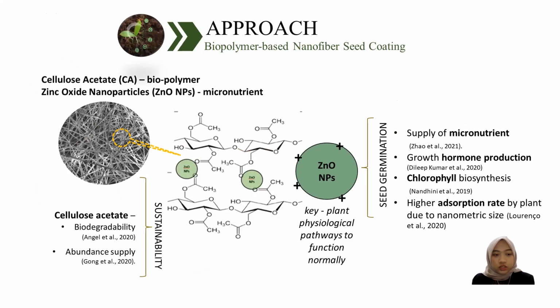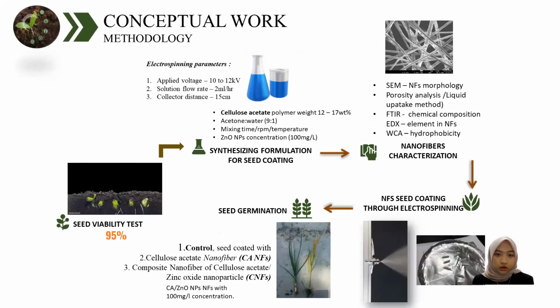The materials that we are focusing on here are cellulose acetate and zinc oxide nanoparticles. Cellulose acetate is a biodegradable product and has abundant supply all over the world. Zinc oxide nanoparticles are an engineered material with a size of less than 100 nanometers, and they supply micronutrients for seed germination, and are also connected to the lack of zinc supply in agricultural soil. Thus, with the inclusion of zinc oxide, it can supply the micronutrients for crop development. Zinc oxide also plays a role in growth hormone production, especially for seed germination and chlorophyll biosynthesis for food production to enhance crop development, and due to the nanometric scale size, it can enhance the absorption rate so it can be easily taken up by the crop.